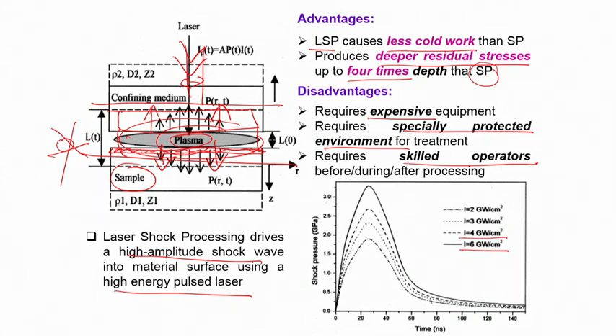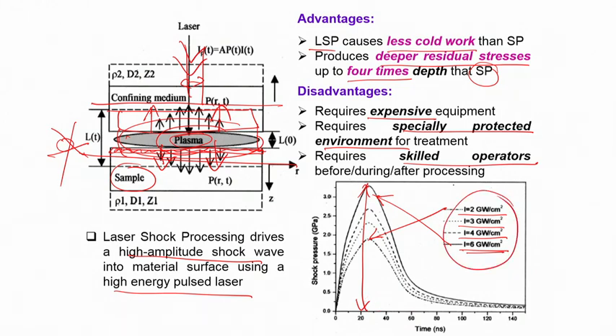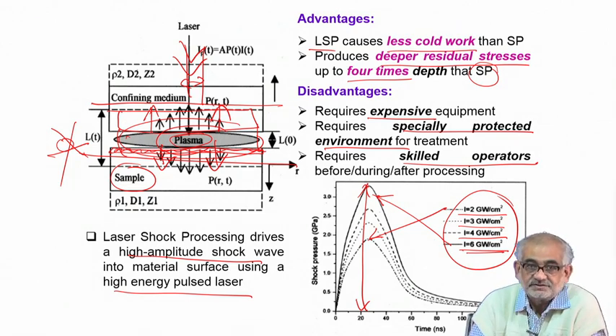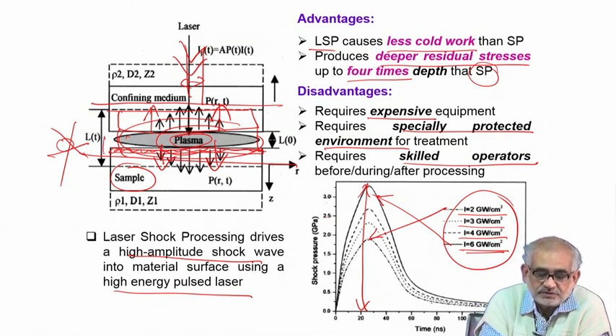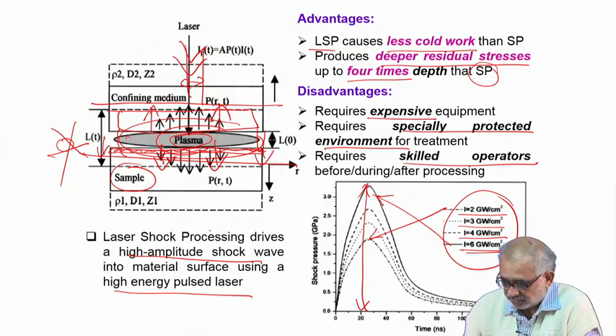Depending on the laser fluence or power density — for example, comparing 2 gigawatt per centimeter squared versus 6 gigawatt per centimeter squared — the shock pressure generated and particularly the maximum pressure amplitude will be much higher at higher power density. The power density of the laser pulses is a very major process parameter. The next important thing is the pulse width. You also have to choose the right kind of coating or film which can instantly generate a plasma that is non-reactive, and if you can also use confinement so that the pressure is mostly applied onto the work piece direction, you derive the bigger benefit.